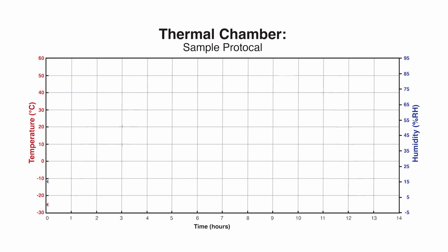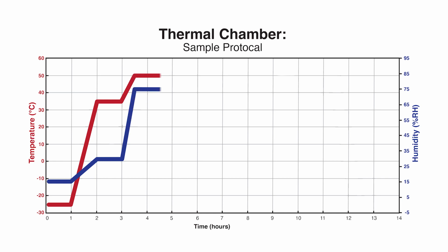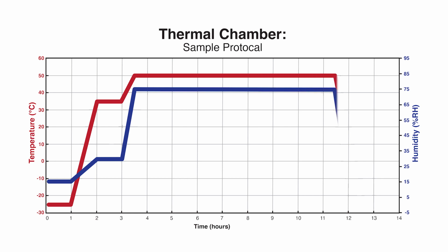For example, this graph shows a sample protocol with a start temperature of -25 degrees C and 15% relative humidity for 1 hour, followed by a ramp to 35 C over a period of 60 minutes and soak at 35 C and 30% relative humidity for 1 hour, followed by another increase to 50 degrees C in 30 minutes and soak at 50 C and 75% relative humidity for 8 hours, then drops the temp back to minus 25 C and 15% relative humidity over 60 minutes to restart the cycle. The chamber can be set to run any number of cycles, from 10 to 10,000.